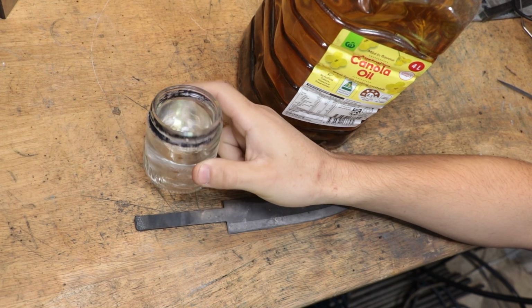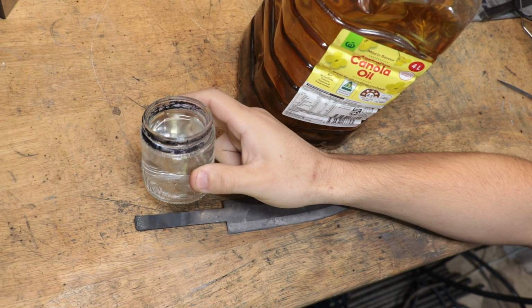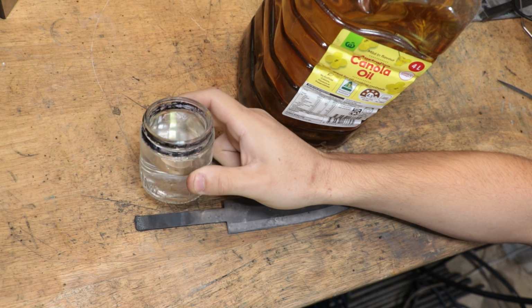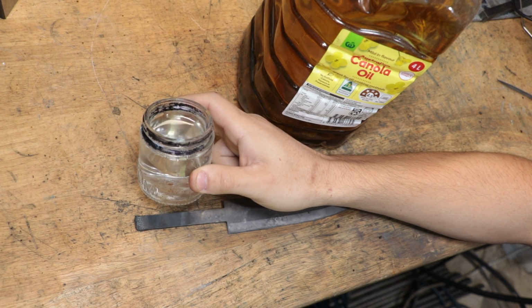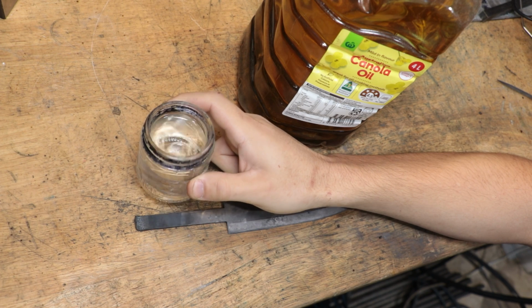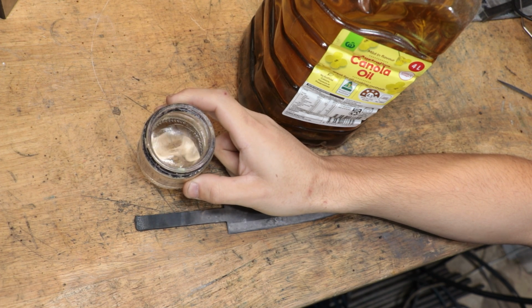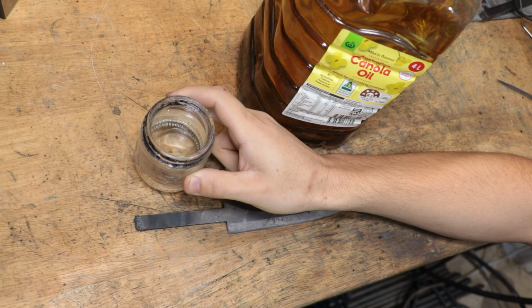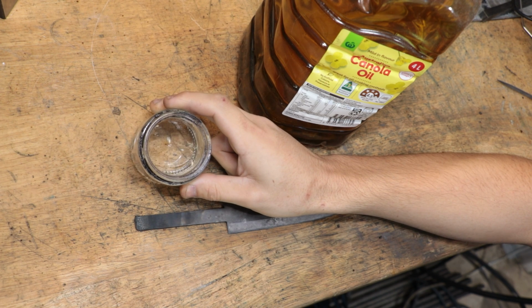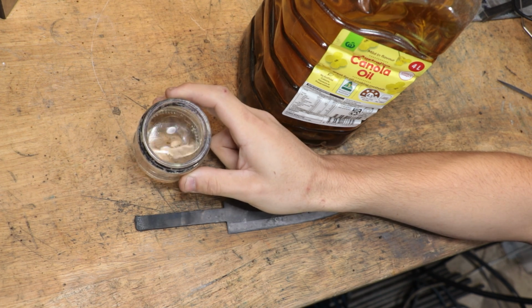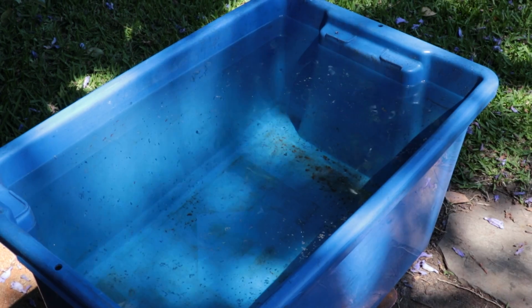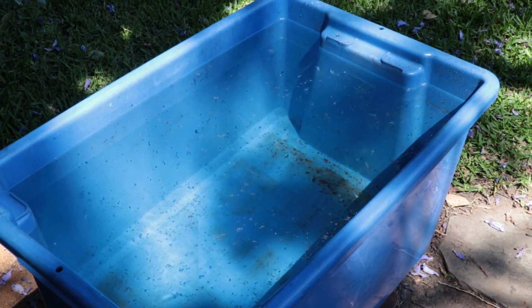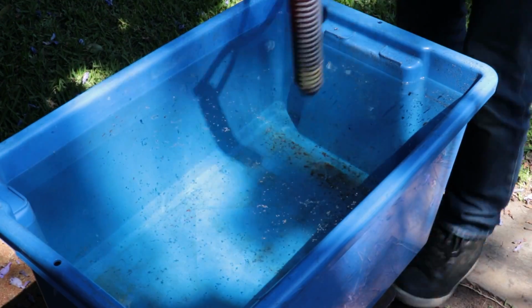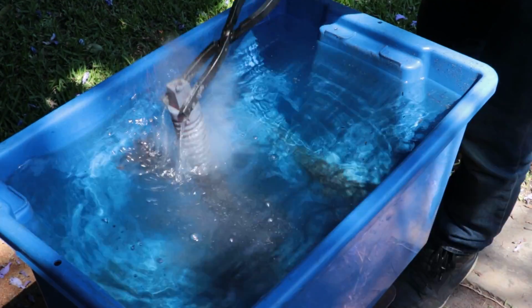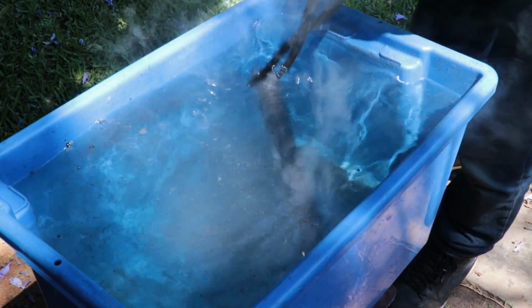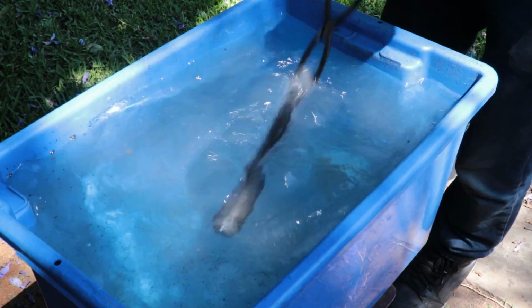Water, and by extension a 10% salt brine solution, is going to offer you the fastest quench for steel, and it's going to give you the maximum hardness, at least for plain carbon steel. And for me, it is my preferred method for quenching parts, not because it gives you the best results, but mostly because it is the easiest method to set up and then dispose of. For some of the parts that I'm doing, I need easily 20 litres of water, and it is a lot easier to set up 20 litres of water in a tub than it is to set up and then clean up and dispose of 20 litres of oil.